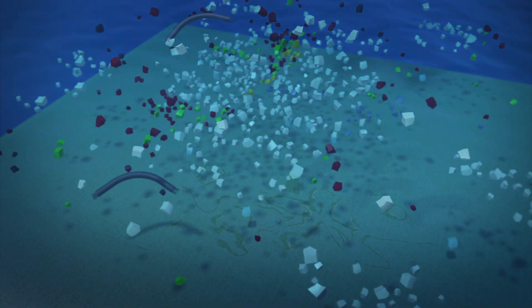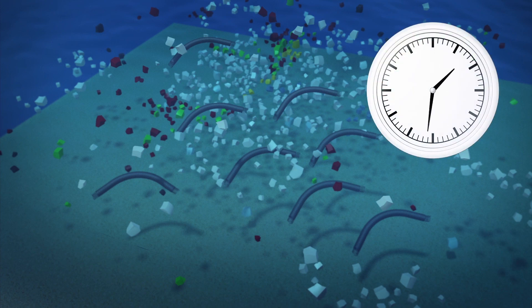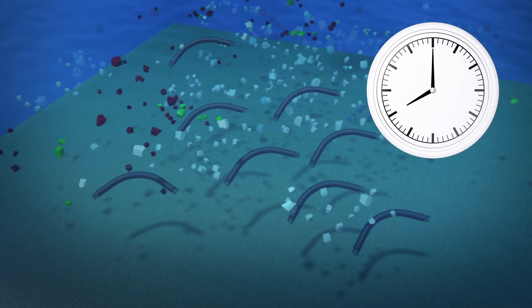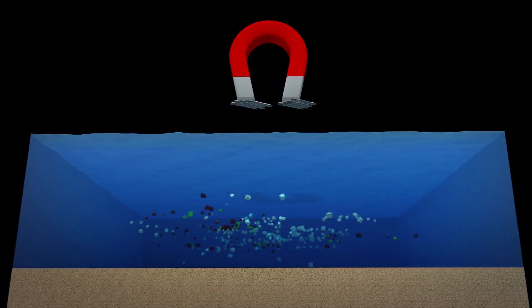During a trial, researchers found that the spiral nanotubes were able to reduce the volume of microplastics present in polluted water by 30 to 50 percent in the span of 8 hours. The nanotubes are retrieved using magnets for later use.